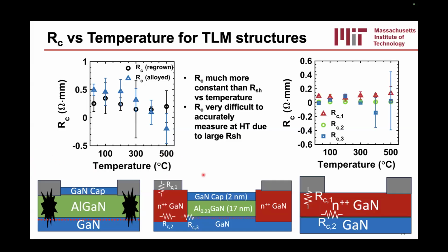Additionally, for the regrown structures, we can actually use those highly doped structures we had measured before, and we can deconvolve the contributions of the contact resistance to RC1, the metal to N++ GaN resistance, RC2, the N++ GaN resistance, and RC3, the N++ GaN to 2DEG resistance. And because the sheet resistance of the N++ GaN is very low and very constant over temperature, we can get very small error bars for RC1 and RC2, as you can see in these red and green circles here. But for RC3, which is the interfacial resistance associated with the contact to the 2D electron gas, that has very large error bars, once again, because it gets difficult to measure when the sheet resistance of the 2DEG is so high at these temperatures. And so the error bars get quite large.